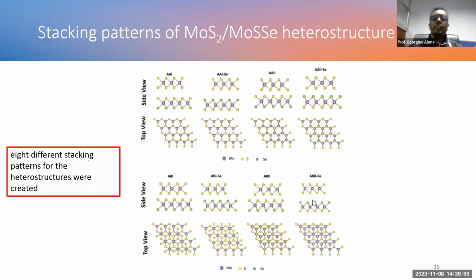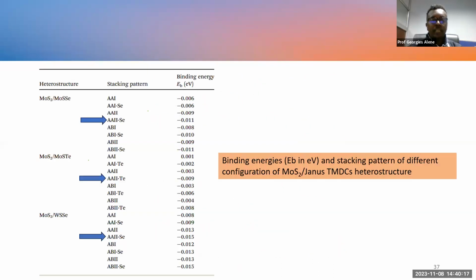And then we follow the same procedure. We make 8 high symmetry stacking patterns using molybdenum disulfide and the Janus materials. So we have 3 Janus materials. So in total, we have made 24 stacking patterns. And from each 8 stacking patterns, we have selected only one, which is the most stable according to the binding energy.